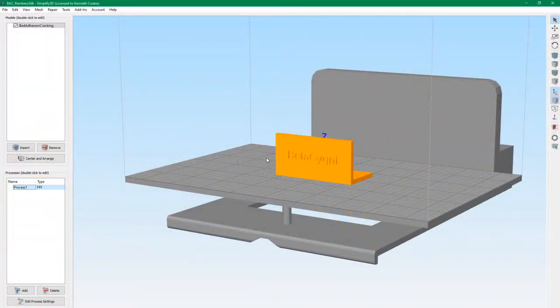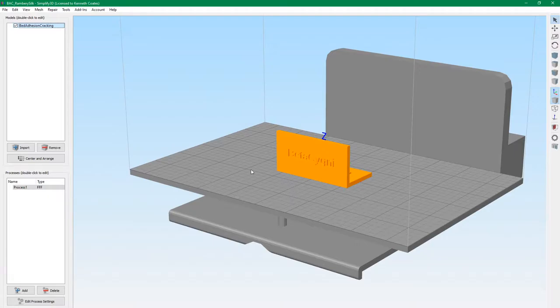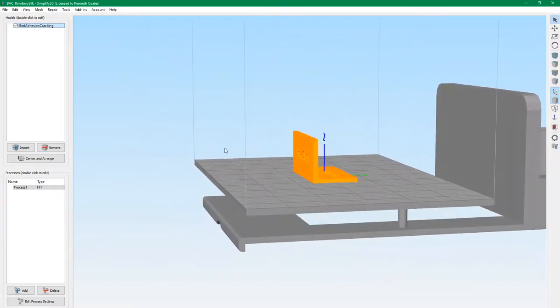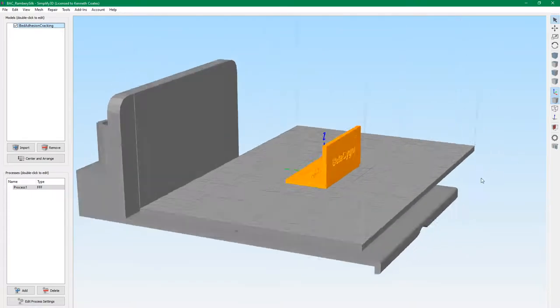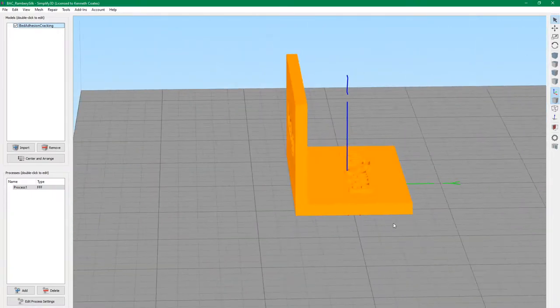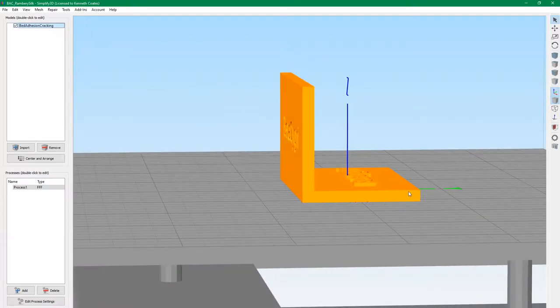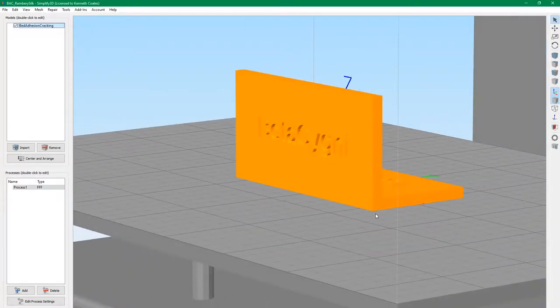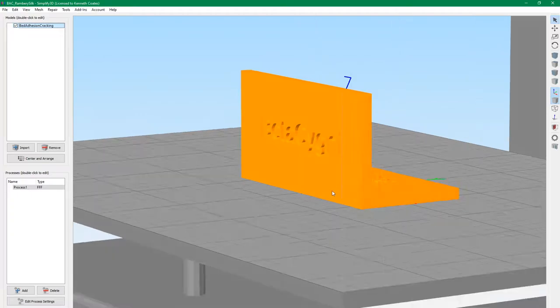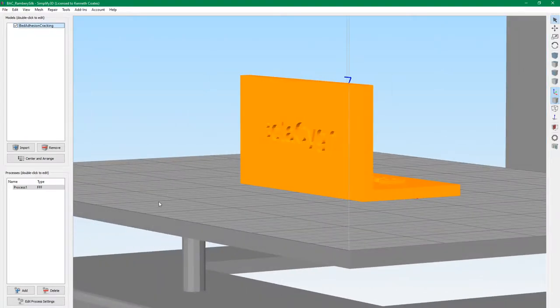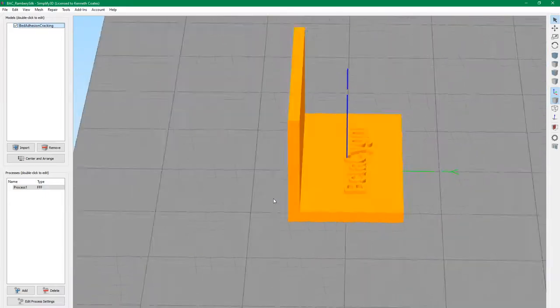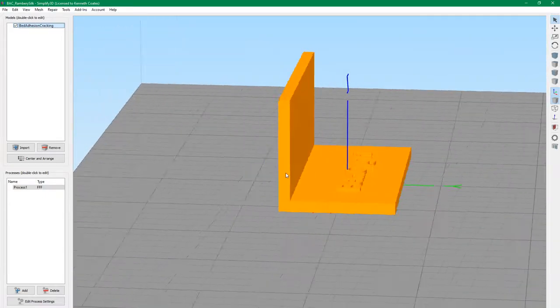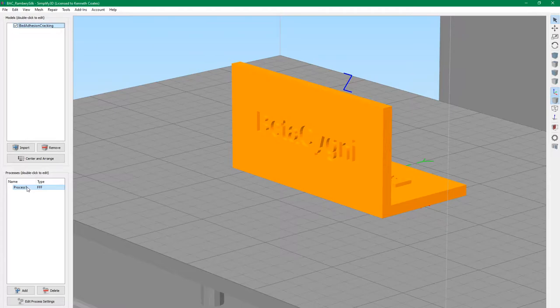All right, the temperature tower turned out like we expected. We're going to be printing at 230 and 40 degree bed temperature. We're going to go on to our next test project we always do with each filament, which is this bed and layer adhesion test. What we're looking for on the bed adhesion is to make sure none of these corners are peeling up. That means we have the bed temperature set correctly and also some indication on the extruder temperature. As far as these layers sticking together, if we get a nice strong joint here and these layers are nice and tight, then we've got the extruder temperature and the cooling set correctly. This test has been really effective for me. There's a link in the show notes to this test on Thingiverse.